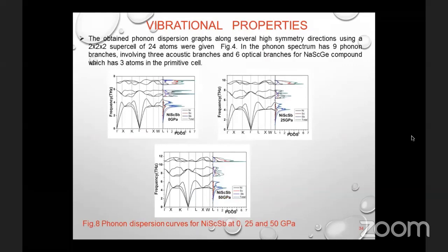That is, dynamical property becomes a more preeminent property of the material. Thus, the phonon frequency of this compound has been obtained using the phonon code. Using density functional perturbation theory, the phonon code obtained the force constant matrix and phonon frequency. The phonon spectrum graph along several high symmetry directions, using a 2x2x2 supercell of 24 atoms, is given in figure 8 for three different pressures. There are no imaginary modes, showing that this material is dynamically stable under pressure. The magnitude of frequency increases with increasing pressure.